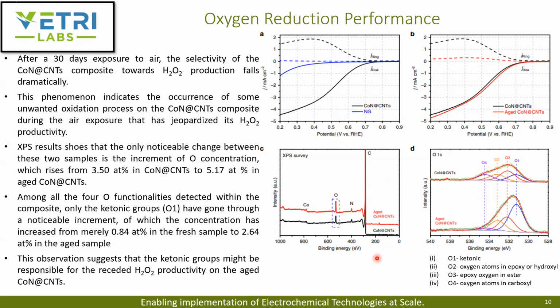So they did XPS to see how the oxygen concentration varied, and what they could see is the oxygen concentration increased from 3.5 atomic percent to 5.17 atomic percent when it was exposed for 30 days.